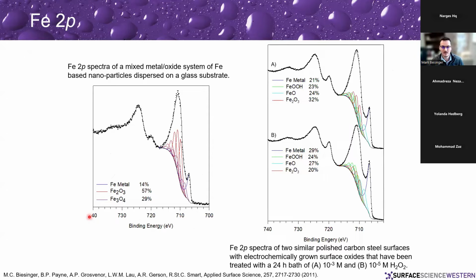That being said, it does work reasonably well if you get good quality spectra, take lots of counts or take lots of scans to get good quality spectra. Be very meticulous about your curve fitting. You can pull out how much iron metal versus Fe2O3 and Fe3O4 that you get. We have some comparisons here where we have the metal with FeOOH, FeO, Fe2O3, slight changes in the chemistries, and we can see some changes in the amount of the different things that are present. And it made sense in the systems that we were looking at.